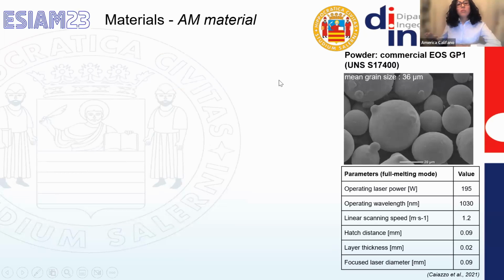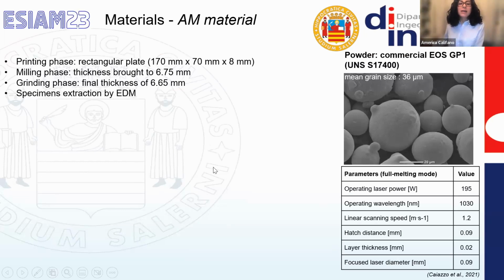So considering on one hand the additive manufactured stainless steel, on the right here you can see a picture of the used powder, and in the table you can see the printing parameters. At the end of the printing phase, a rectangular plate with a thickness of 8 millimeters was obtained. Then the plate was milled and finally ground, and a final thickness of 6.65 millimeters was reached.